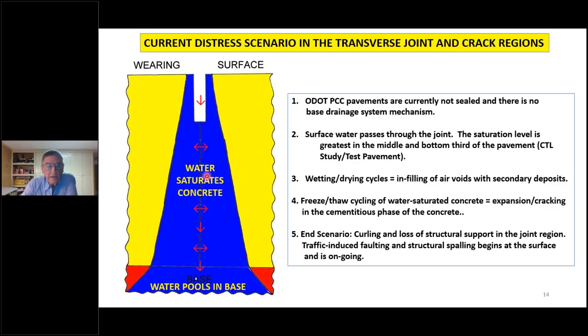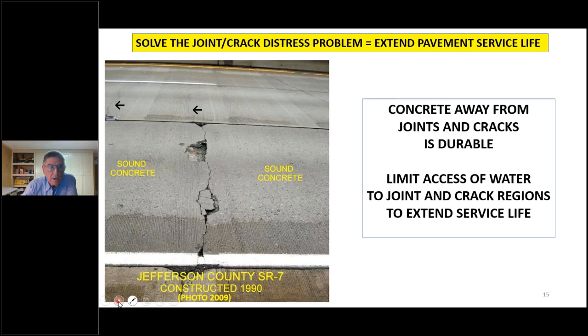So you have the water saturating the concrete, and then over the months and years, wetting and drying cycles, the freezing and the infilling of the air voids, subsequent freeze-thaw cycling of the water-saturated concrete, and then cementitious phase, with the end scenario being curling and loss of structural support in the joint region. So you get the traffic-induced damage beyond that time, and of course that's ongoing and getting worse and worse. So the obvious logic there is if you solve the joint crack distress problem, you're going to extend pavement service life. And to that end, I talk about this whole situation.